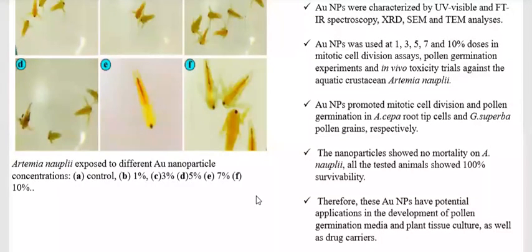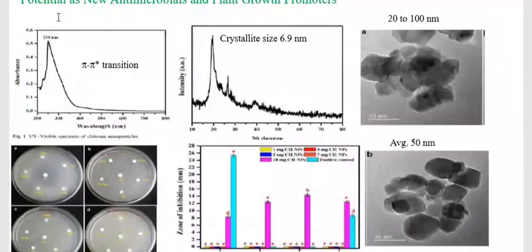Next slide, ma'am. Fifth chapter, chitosan nanocrystals used as potential antimicrobial agents and plant growth promoters. Everyone knows the biopolymers. Cellulose is the first polymer. The second most abundant polymer is chitosan, derived from shrimp, crabs and fungal material. The synthesized chitosan nanoparticles show a peak at 250 nanometers to confirm the chitosan nanoparticle. It shows the XRD analysis.